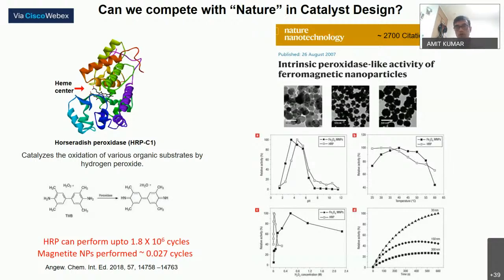for the enzyme to function. More than 10 years back, a paper came out in Nature Nanotechnology which invoked the enzyme-like activity of iron oxide nanoparticles, and it has got about 3,000 citations so far. But if you compare the activity of these nanocrystals with the enzyme, HRP can perform close to 2 million cycles within 5 minutes of reaction time, whereas these magnetite nanoparticles cannot even do one cycle within that time. So compared to natural systems, the synthetic systems are very weak in performance.